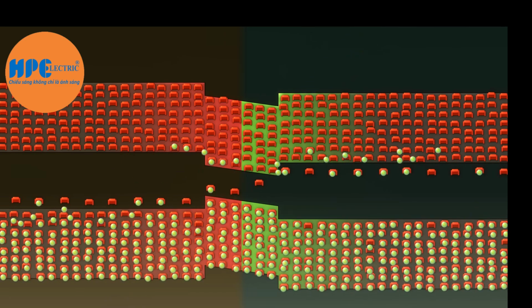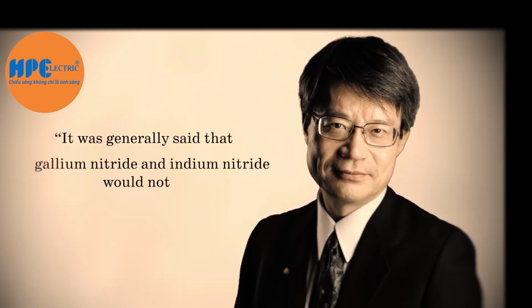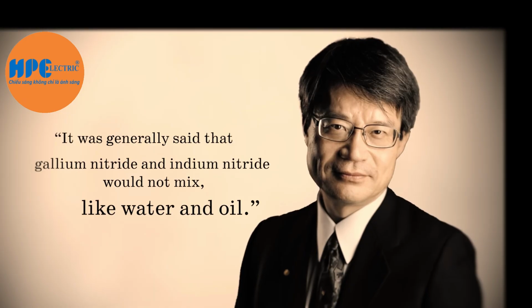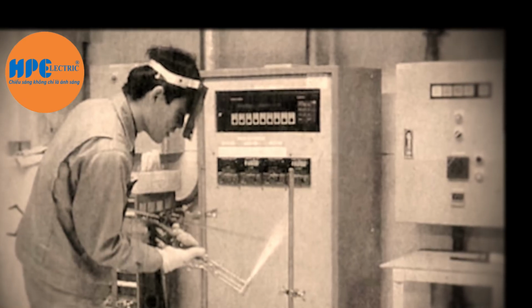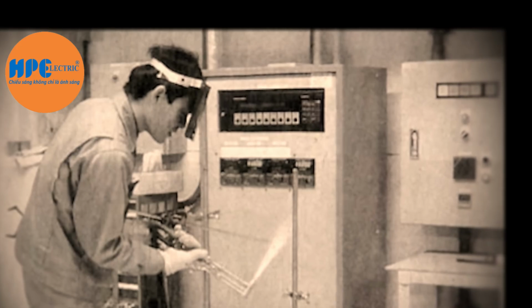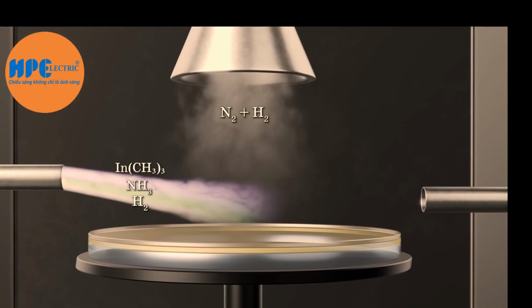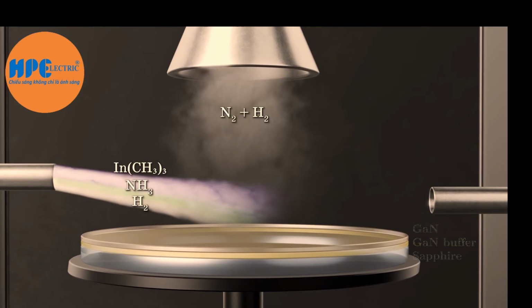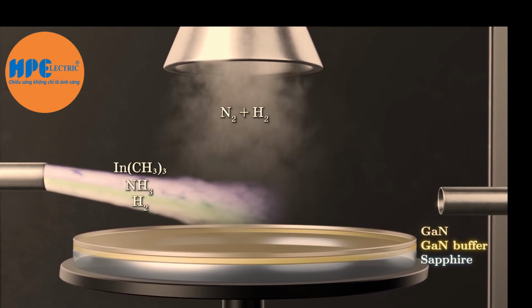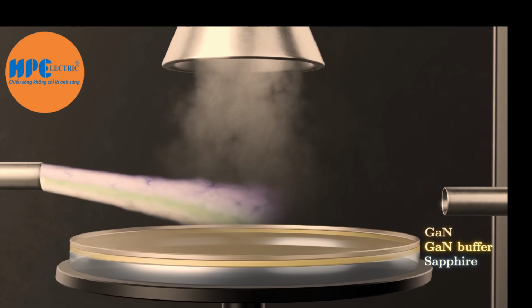to true blue. This time, Akasaki and Amano didn't scoop Nakamura. They were stuck trying to grow indium gallium nitride in the first place. Amano recalled, "It was generally said that gallium nitride and indium nitride would not mix, like water and oil." But Nakamura had an advantage: his ability to customize his MOCVD reactor. This allowed him to use brute force, adjusting the reactor to pump as much indium as he could onto the gallium nitride in the hopes that at least some would stick. To his surprise, the technique worked, giving him a clean indium gallium nitride crystal.